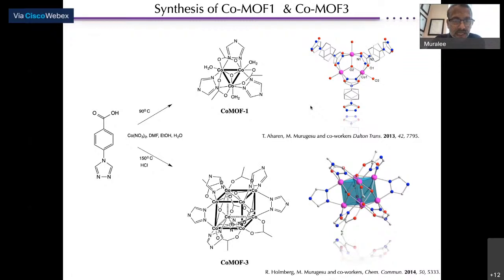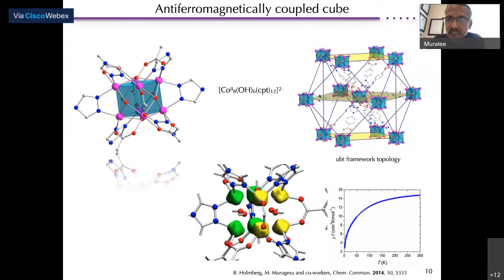Slightly changing the reaction condition, adding 1 drop of HCl and heating it at a higher temperature, we can make this beautiful supercube SBU for this MOF. And if you look at the structure, these SBUs are linked by this asymmetrical linker into 3-dimensional UBT framework topology. We got excited about this structure and thought this is one of the coolest SBUs that I have personally seen, and it is formed with magnetic metal centers of cobalt. So we hoped that we would have a nice metal organic framework that acts as a magnet.